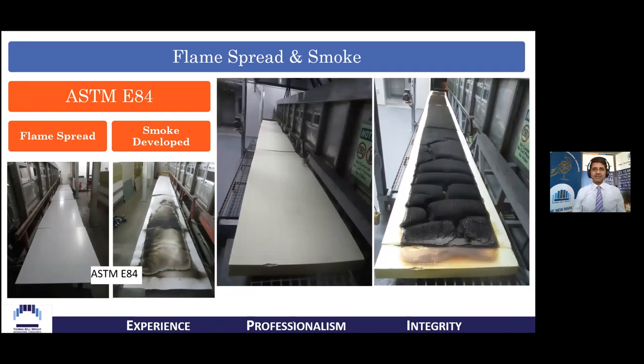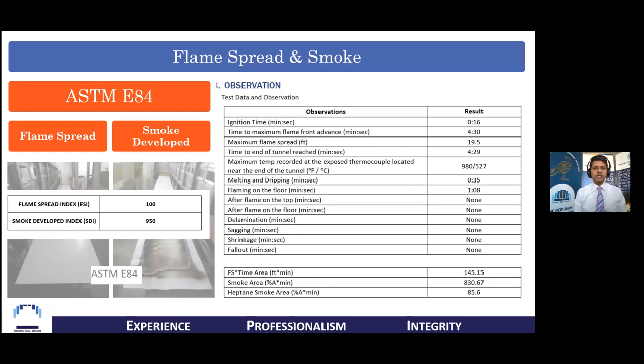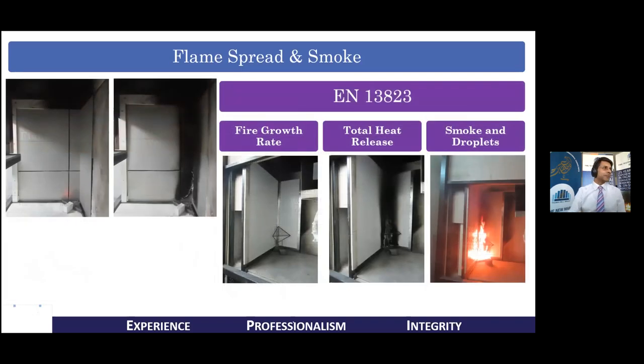Now, any other product or material, which could be a plastic, a composite, a mixed material, a coated material, when it is burnt in the Steiner tunnel or this test equipment, relative to these two numbers, a number is arrived at. So you can almost imagine that certain types of plastic, which burn faster than red oak wood, would have a flame spread index number much higher than 100. So the result of such a test is a usually bland looking, saying, well, the FSI and SDI is 100 and 950. And typically this number may not really make sense, but this number is used by creating classifications of A, B, C, and I'll come to that later, and then used to create demarcations of the types of products or materials that should be allowed for a given application or should not be allowed for another given application.